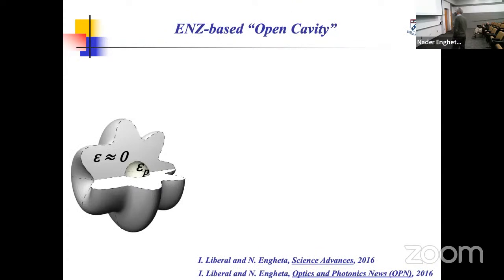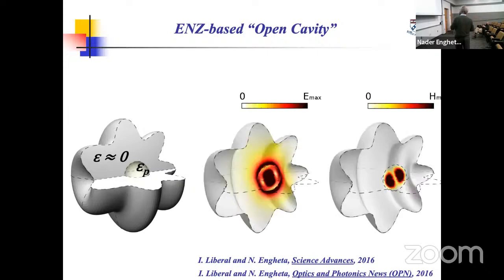So essentially, think about this. Imagine that you have a structure like this, a three-dimensional epsilon near zero structure, and you put a dielectric there. And that dielectric core can be any place you want, by the way. And this cavity is an open cavity, so there is no metallic wall on the boundary. It's just open. It turns out that this structure has a very interesting electromagnetic mode. And what I show over here is the electric field distribution, which is this plot, and the magnetic field distribution of that mode over here.